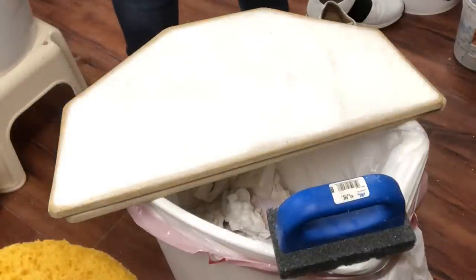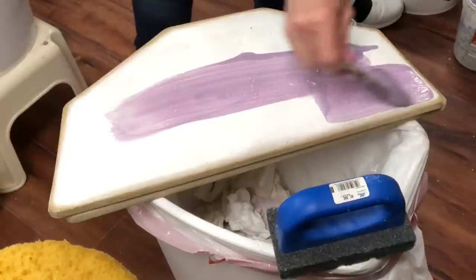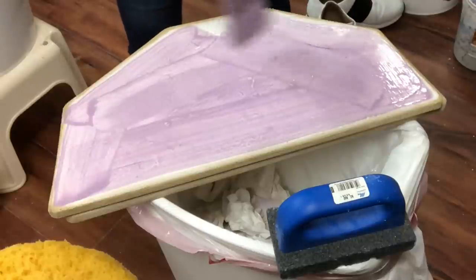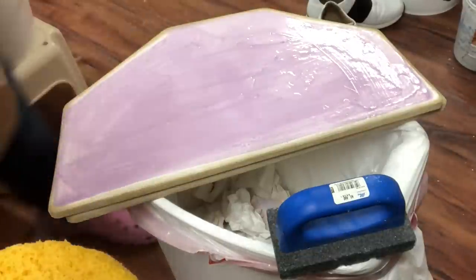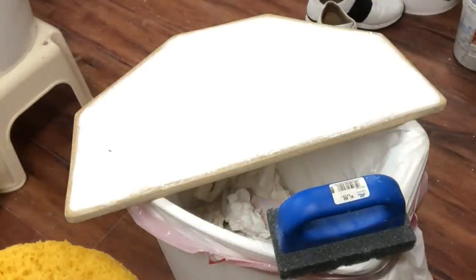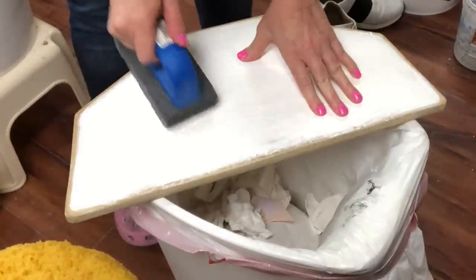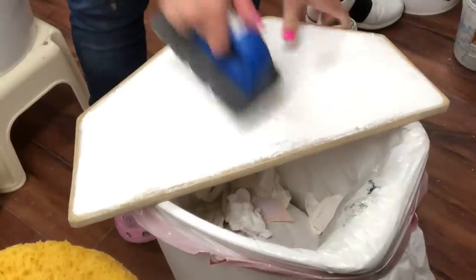After it's been scraped and sponged, I apply a very thin layer of kiln wash. You want the layers to be thin so it doesn't flake off — if kiln wash is flaking off during a glaze firing, it can actually go airborne and float around the kiln and land on your items. You only kiln wash one side of the shelves; the back side is never kiln washed because it would fall off and get on your pieces underneath.